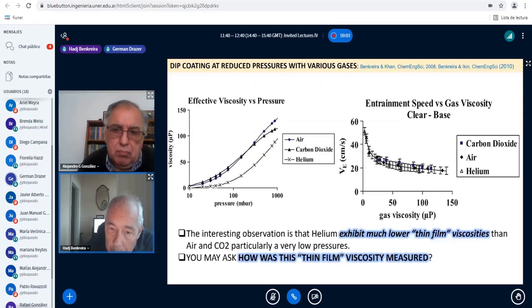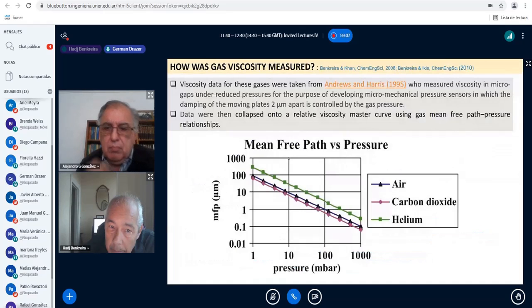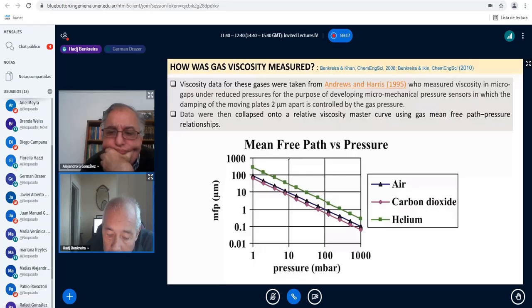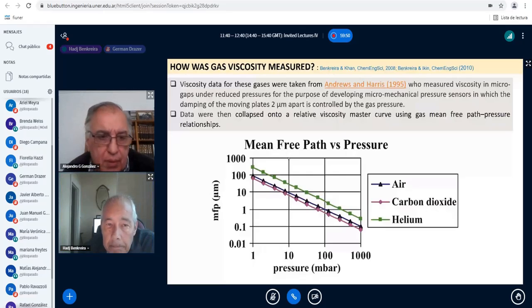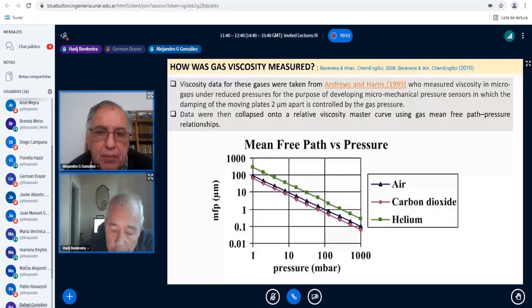As you mentioned, it's different from bulk, so wouldn't it depend on that 2 microns? If it is 1 micron or 10 microns? Yes, certainly, it has to be. And this is the assumption. Ideally, as low a separation as possible, but you can imagine, at 2 microns apart, that was pretty small for us. But of course, if it is going to be a millimeter, it won't be good enough. It will be. Thank you. In that situation, it will be bulk viscosities, which will not change very much.